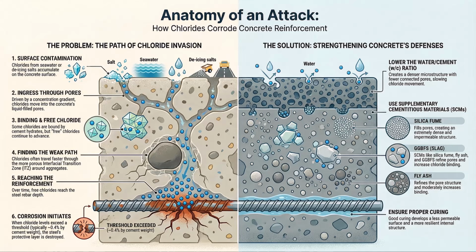That's the perfect analogy. And the raw numbers are really telling. Arabian Gulf seawater, which is what's battering the coasts of the KSA Eastern Province and the UAE, ranges from 19,000 to 22,000 milligrams per liter of chlorides. And how does that compare globally? Well, the Red Sea around Jeddah and Neom is also very high, 18 to 19,000 milligrams per liter. That's comparable to the Atlantic Ocean reference, which is around 19,000. But the Arabian Gulf often significantly surpasses that. So we're starting with an incredibly high external concentration.